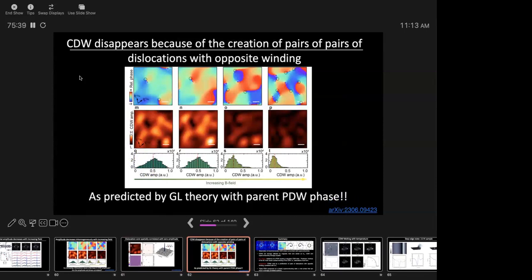So this is very consistent with the idea that you have a pair density wave creating a charge density wave. If you didn't have a pair density wave, then this whole mechanism would fall apart, and there's no simple way of getting these dislocations. Yes? Go ahead.